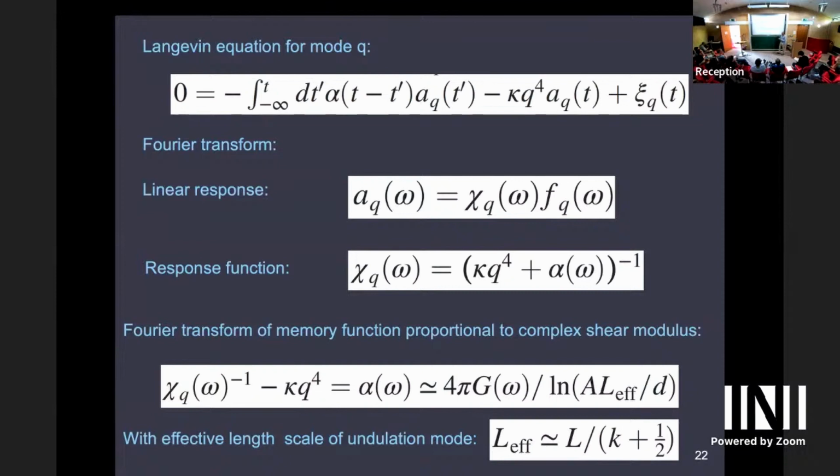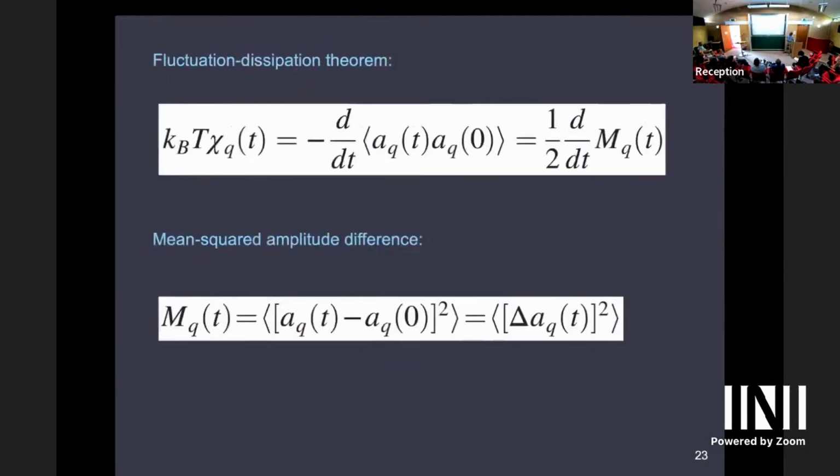Of course, it's not a huge scale range that you can test, but like a factor of 2 or 3 or 4, with the higher modes. So that's the way to evaluate those data. And then, of course, some practical issue is how do you do that? I wasn't going into the details. We used to use Kramers-Kronig relations to first get the imaginary part and go to the real part, but it has some disadvantages. It makes it asymmetric.